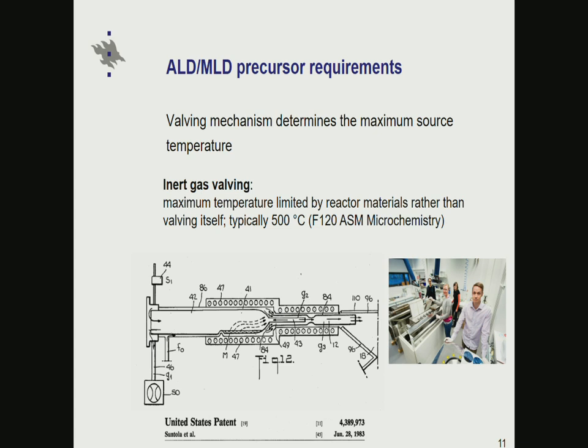So what is the maximum source temperature one can use to evaporate the precursors? The best one can get is actually shown here. This is inert gas valving, and our group is more or less spoiled to have that available. I don't have time or need to go into details here, but in inert gas valving, the valving action, determining whether the precursor is coming out from the source or not, is realized by controlling gas flows in between the source and the chamber. These flows can be controlled by mechanical valves, which are themselves at room temperature, yet the valving action itself is there at the temperature where the film growth is taking place. So it can go up to 500 centigrade or even higher in our research scale reactors.